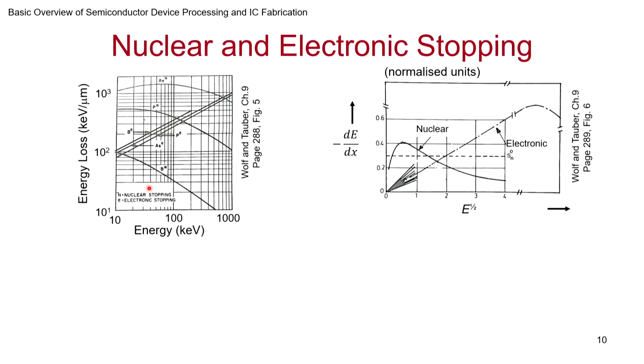So, if you notice here, the nuclear stopping values are given here, and the electronic stopping values appear as a straight line. So, what it tells is initially it is linearly changing, then there is a maximum amount, and then after that the loss of energy is less and less and less. Okay. So, that is what you find. On the other hand, electronic stopping keeps going up.